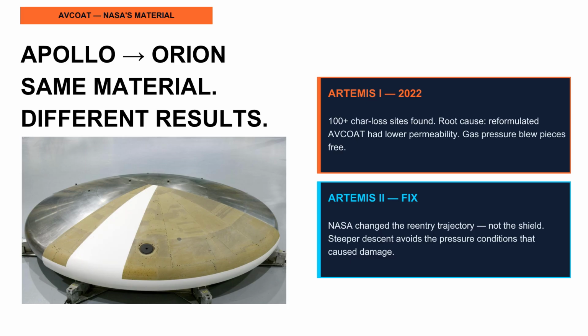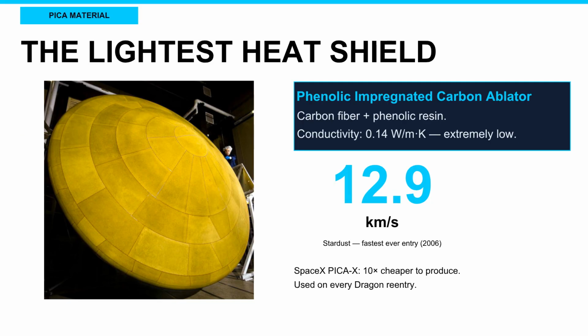Others publicly did not. PICA, phenolic impregnated carbon ablator, was developed by NASA Ames Research Center in the 1990s. Carbon fiber preform is infiltrated with phenolic resin. During heating, the phenolic pyrolyzes, releasing gases. The carbon fiber structure remains as a low-density insulating char. PICA has a very low thermal conductivity. It is also extremely lightweight.